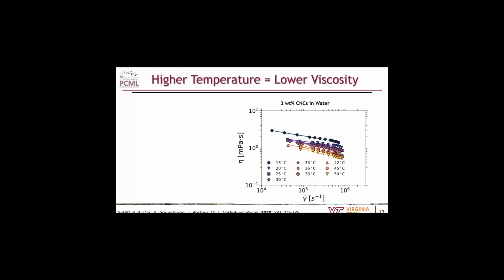What we are looking at, just to start off, because no one's really done this work before, we just got some basic shear sweeps, and we changed the temperature. Some fairly obvious things to notice is as you increase the temperature, you decrease your viscosity. That's fairly standard for most materials, especially Newtonian, such as the water that we're suspended in.